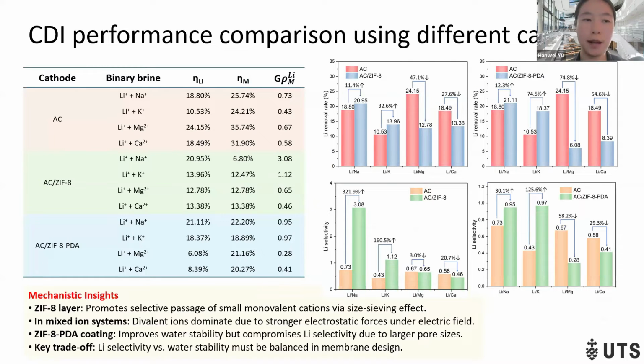Here's the comparison of CDI performance among these different cathodes. We found the ZIF8 layer promotes the selective passage of small monovalent cations via the size-sieving effect. In mixed ion systems, the divalent ions dominate due to the stronger electrostatic forces in the electric field. And the ZIF8 polydopamine coating improved the water stability, but compromised the lithium selectivity due to large pore size. Here's a key trade-off: lithium selectivity and water stability must be balanced in membrane design.